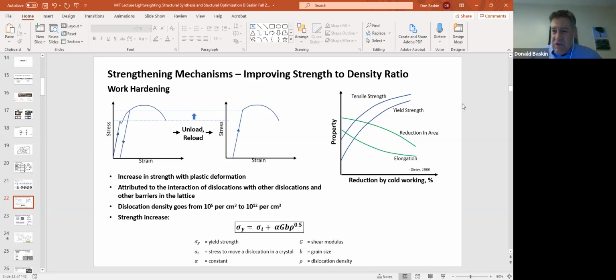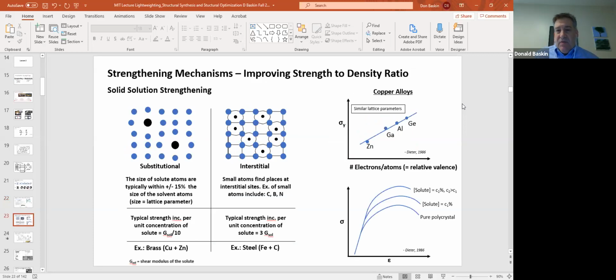So the yield strength, like I said, with this cold working, that's this deformation, it's called cold working, the yield strength goes up, but the elongation of the material, the amount you can deform it until it breaks, goes down. Another mechanism to impede dislocation motion and therefore increase the strength to density ratio is called